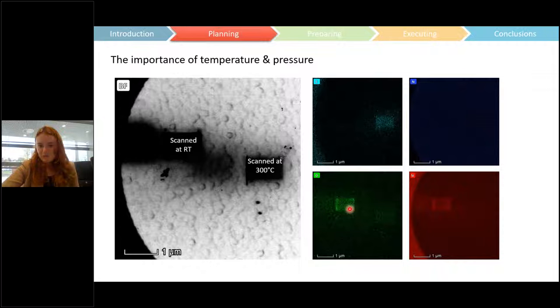What is the difference between room temperature and 300 degrees? Well, obviously, the main thing we could come up with was probably that it was water contamination. So we started looking into this and thinking, wait, silicon nitride window plus water plus beam seems to be forming the silica. And we reported this to quite a few people. We brought it up at conferences. We brought it up to professors. And we were sort of told, oh, no, don't be silly.